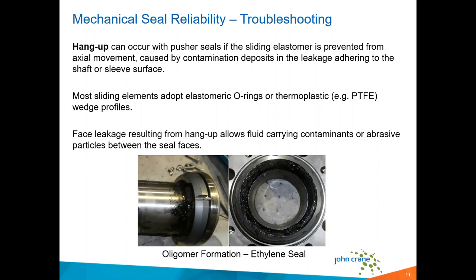the atmospheric side of a seal, and this again resulted in a couple things: higher elevated levels of leakage, and also localized conditions where seal face temperatures were running much hotter than anticipated. So in this case, the problem was corrected by adjusting some parameters in the seal faces, implementing a little different face technology to lower temperatures and improve lubricity. And so that cut down quite a bit on the localized temperatures, but there were also some process related operational issues here as well in terms of start stops that were potentially contributing to the condition that you see here.